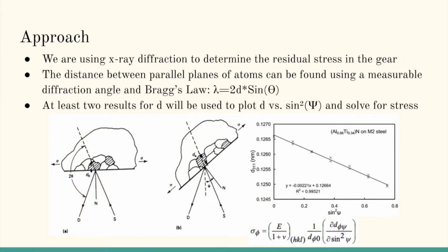The distance between parallel planes of atoms can be found using a measurable diffraction angle and Bragg's law, where lambda is the wavelength of the X-ray, d is the distance between parallel planes of atoms, and theta comes from a measurable 2 theta, which is the angle between the extended incident beam and the diffracted beam seen in figure A below.